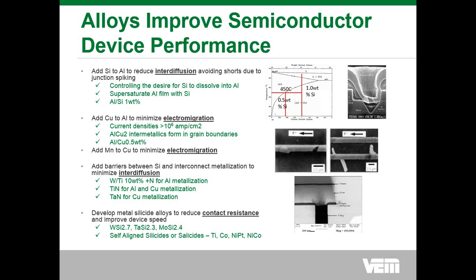In the copper metallization world, people are starting to add manganese for the exact same reason, to minimize electromigration. But if I go back up to that aluminum silicon phase diagram, you also see that at room temperature, the solubility of silicon in aluminum is very low. And what does this lead to? It leads to the formation, when the device goes back to room temperature, of silicon precipitates in contact windows.